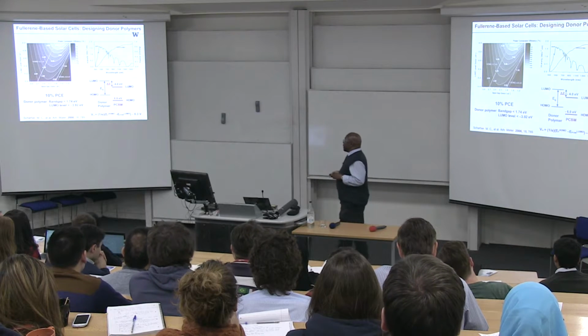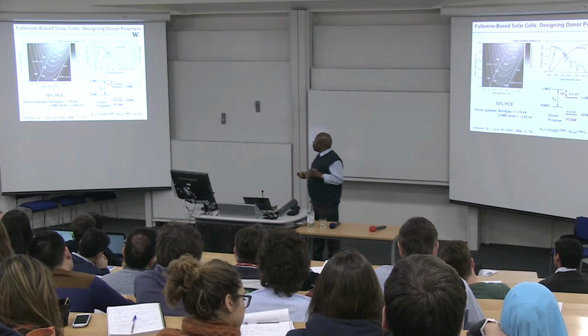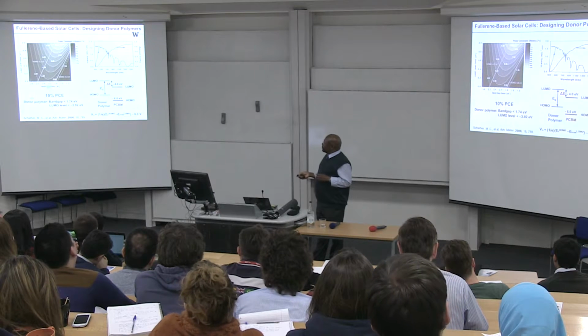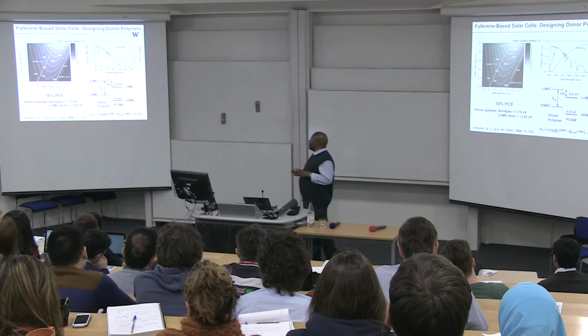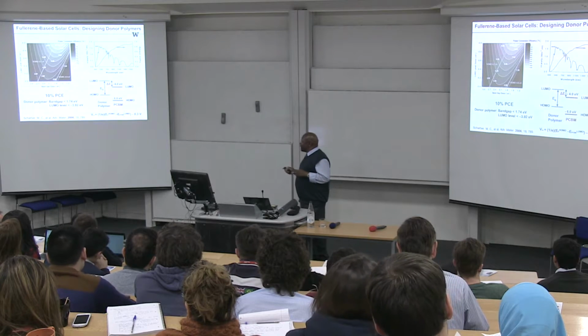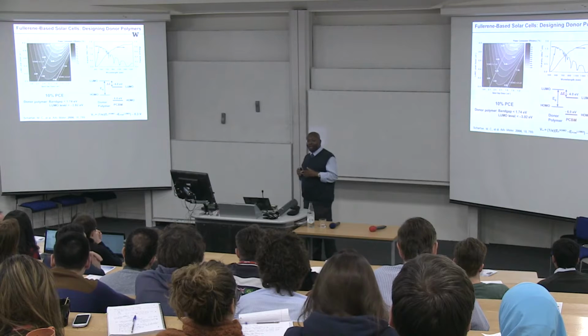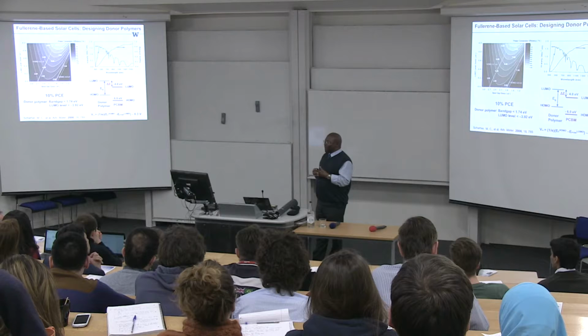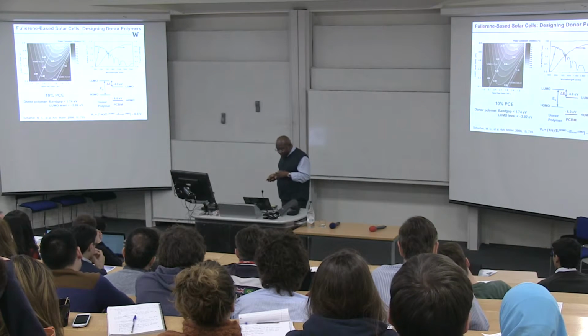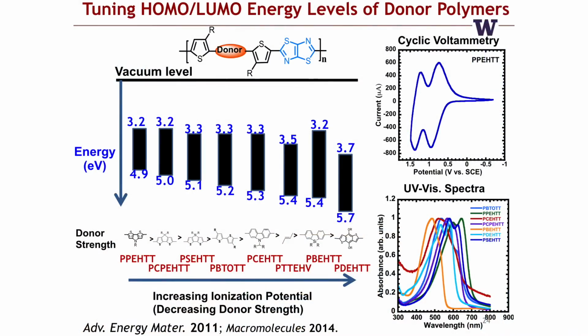And what is interesting is it was determined that if you use PCBM as the acceptor material, the donor that has a band gap on the order of 1.7 electron volt or so, with a corresponding LUMO in this range, will probably be a good target to be able to reach 10% power conversion efficiency. And so many people have subsequently tried to follow this approach in trying to design materials. The approach doesn't work very well, but it has provided some guide, and we and others have used it to try to design polymers that can at least shed light on how we can improve device efficiencies.